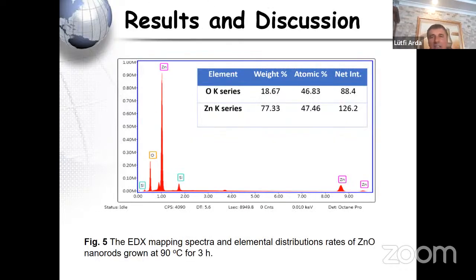In this figure, the elemental concentrations of zinc and oxygen are 77.33 and 18.67 weight percent respectively, while they are 47.46 and 46.83 atomic percent. We characterized all the nanorods, and the next step is the optical properties.